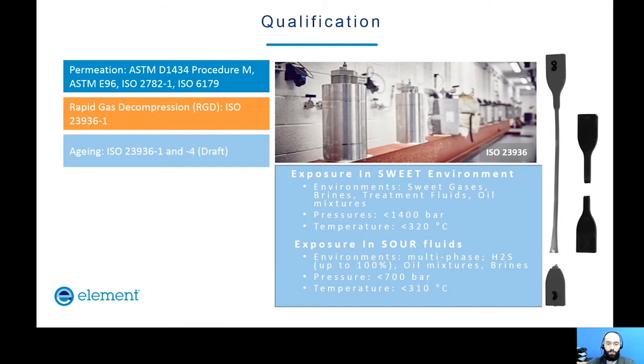And hence, the important parameters that need to be checked are the effect of the fluid that ages the product on the mechanical integrity of the composite, which is of particular importance, and accelerated aging has to be used for reaching these conclusions. For that we use the Arrhenius equation by increasing the temperature relative to the Tg of the material at the time of the exposure.